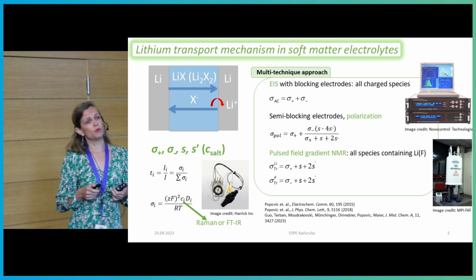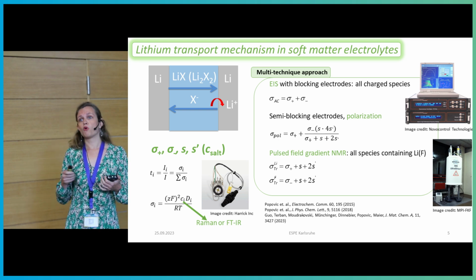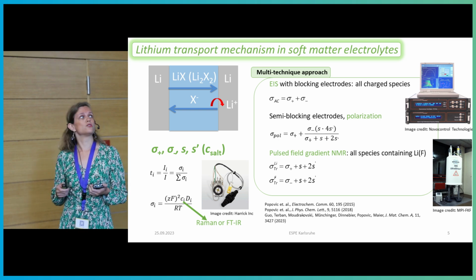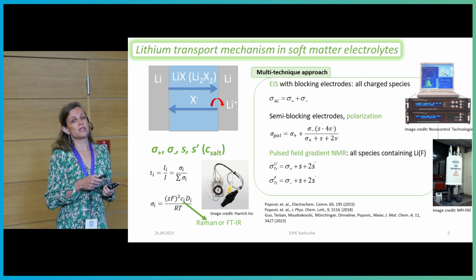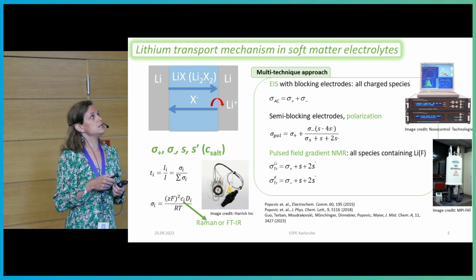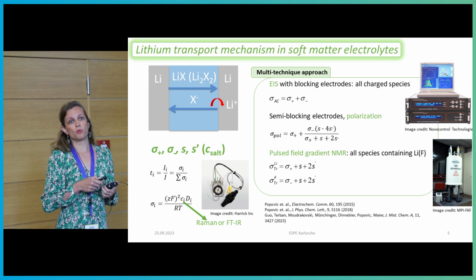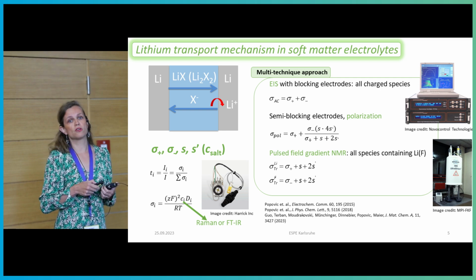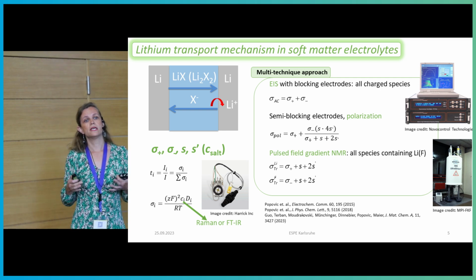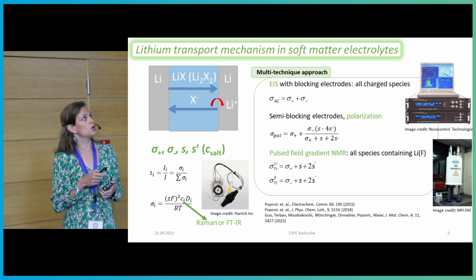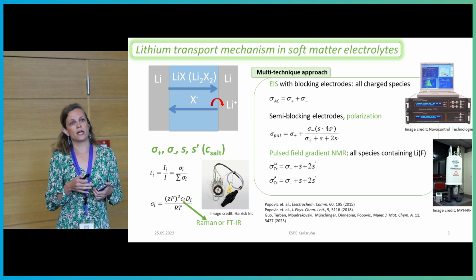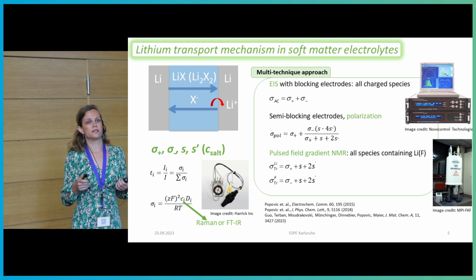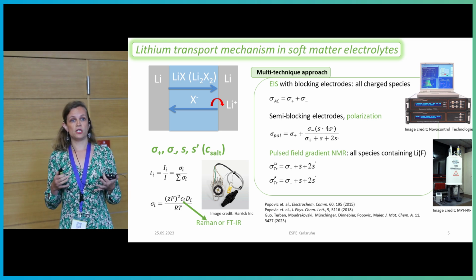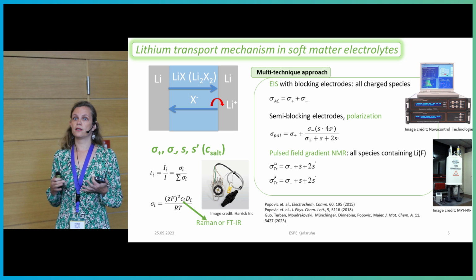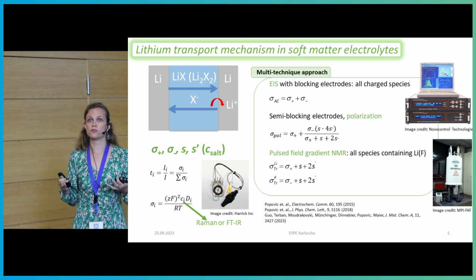Which means that we could actually have a correlated movement of ions just because we have semi-blocking electrodes. What does it mean? It means that the lithium can enter on both sides, and we have concentration gradients of all of the species that appear in these kinds of electrolytes, including the ion pairs, the ion doubles, and any other species that are there. And as I said, the association constant is complicated, and the number of species is dependent on the concentration.